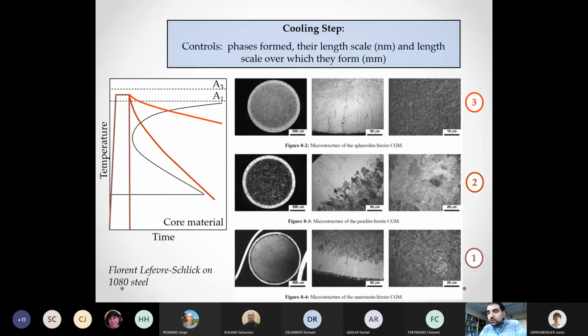Next, just an example here on what we can do with the cooling step. So there is the initial decarburization step, and then there is the cooling step. Depending on the cooling rate, we can make microstructures where we have ferrite on the outside and a spheroidite structure on the inside. So these will have very nice ductility. We can make something with ferrite on the outside and pearlite on the inside, or we can make, of course, ferrite on the outside and martensite or bainite on the inside. So these are all examples from the same steel and just different microstructures by controlling the cooling step.